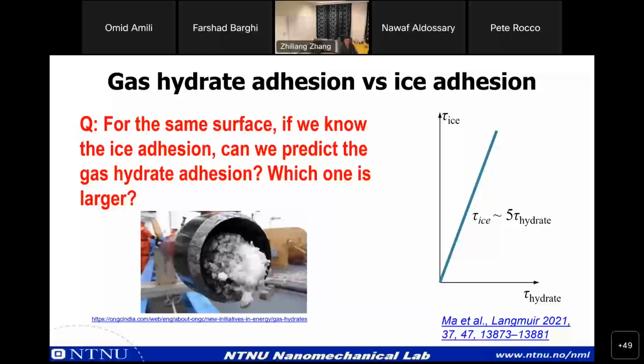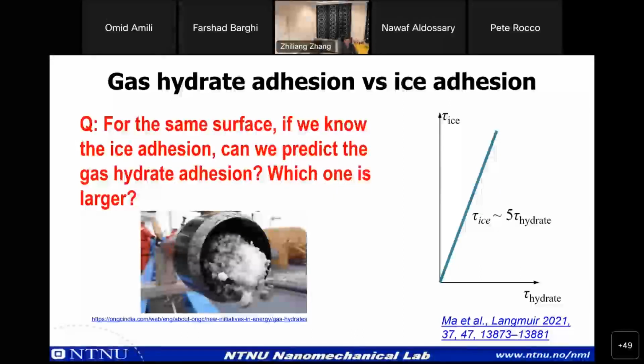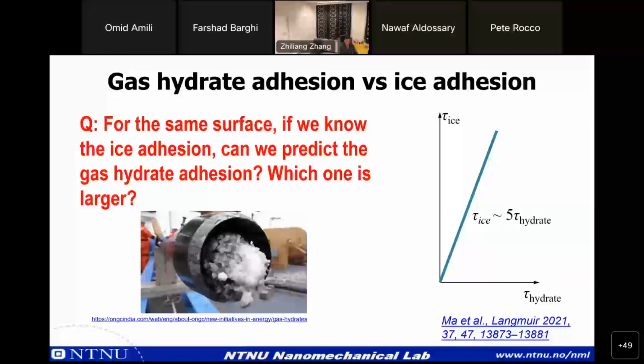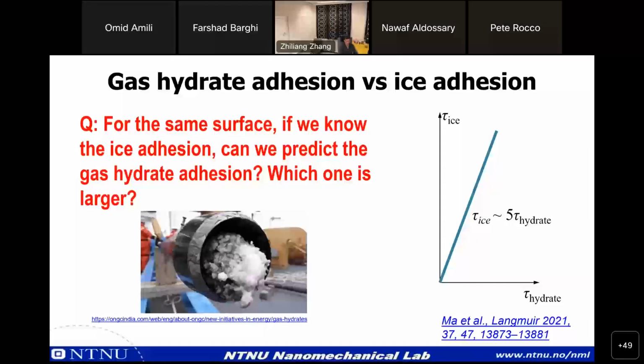We can plot the vertical axis as the ice adhesion. The horizontal axis is the hydrate adhesion. Ice adhesion is 5 times larger than the gas hydrate adhesion. And this is both experimental observation and also molecular dynamics simulation. I think this relationship is very interesting and very useful for engineering design.